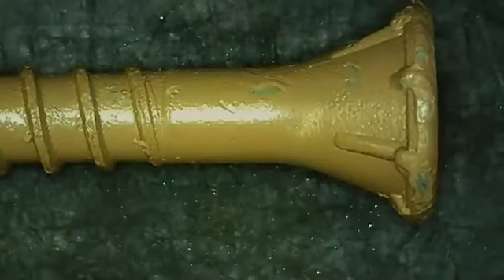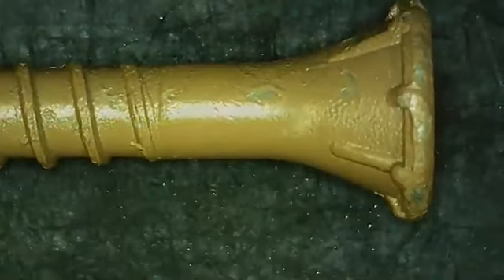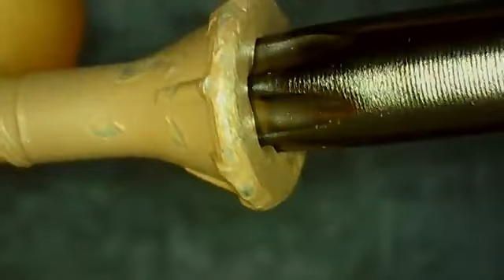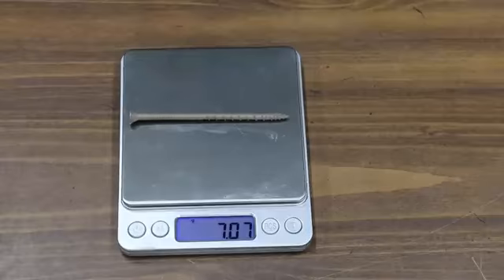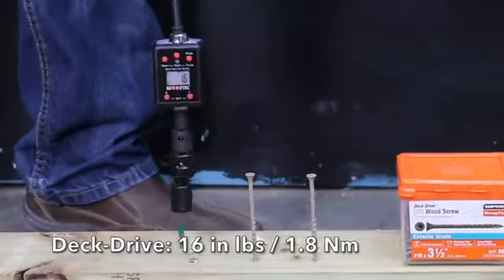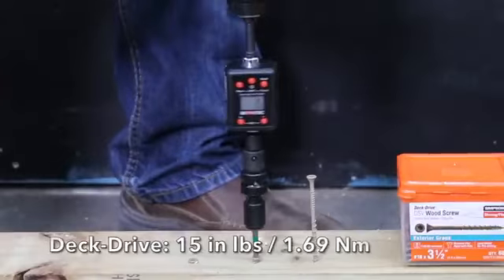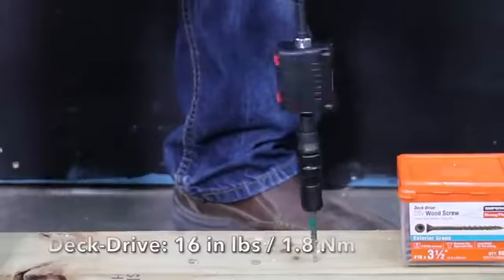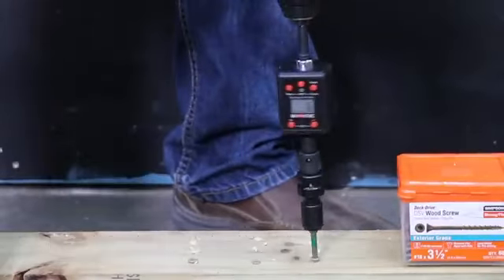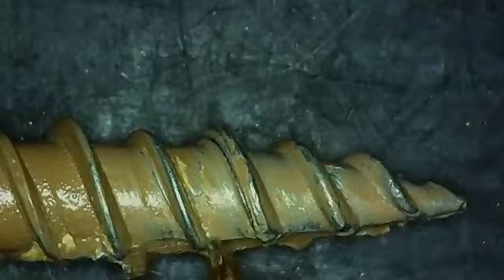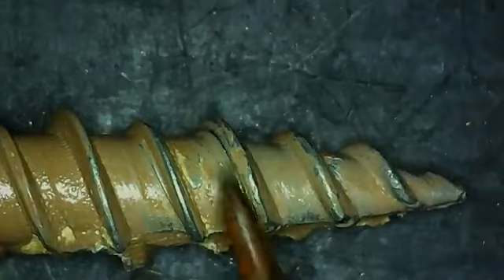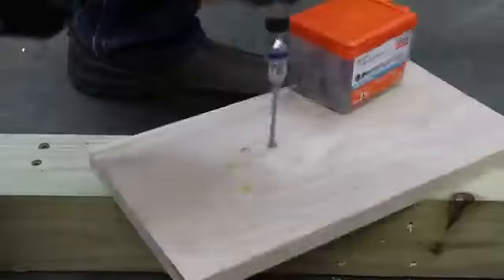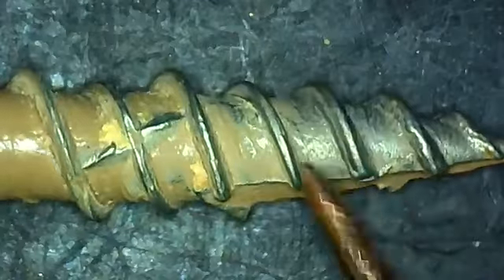The coating on the Deck Drive screw is in the best condition yet with no visible chipping. Made in Taiwan with global materials. The Deck Drive is the second heaviest yet at 7.07 grams. 16 inch-pounds to drive the first screw. The second screw was nearly the same as the first at 15 inch-pounds. 16 inch-pounds on the third screw, so 15.7 inch-pounds on average. The Deck Drive seems to perform about the same as the WoodPro with metal exposure to the threads. And the oak really caused a lot of wear and tear to the coating on the Deck Drive screw.